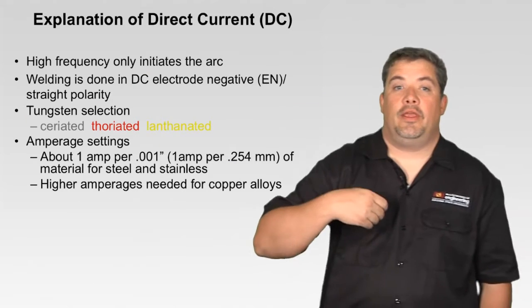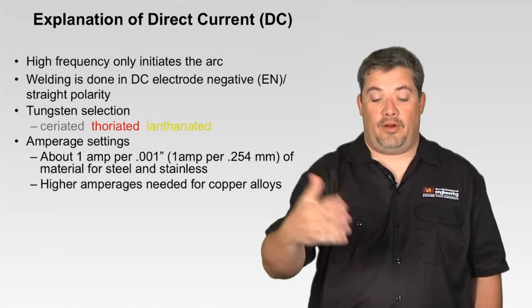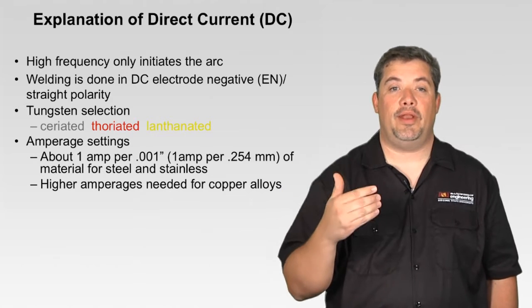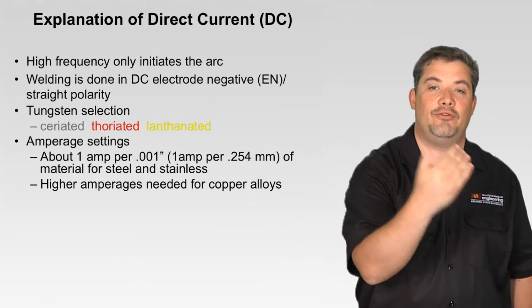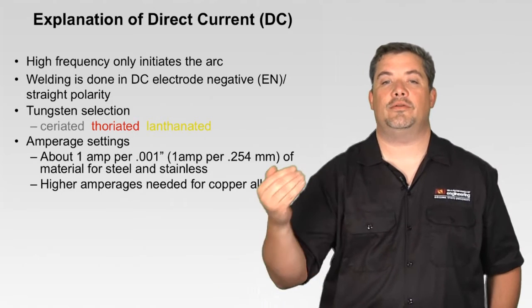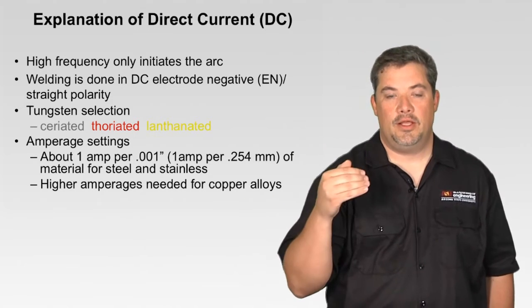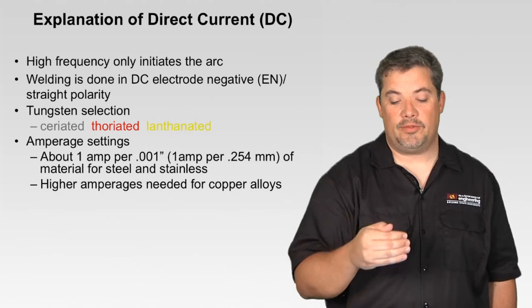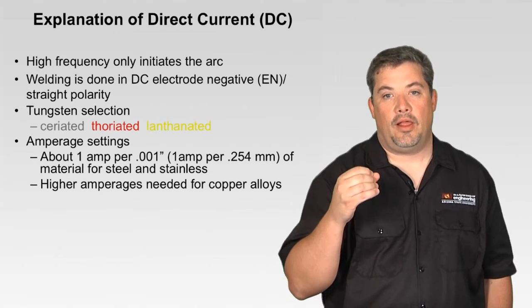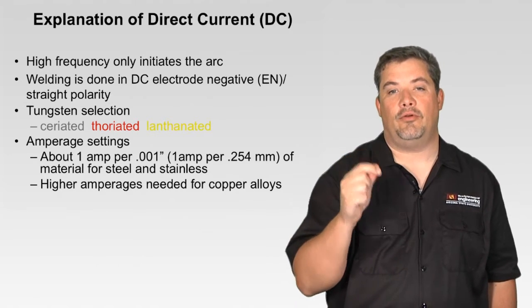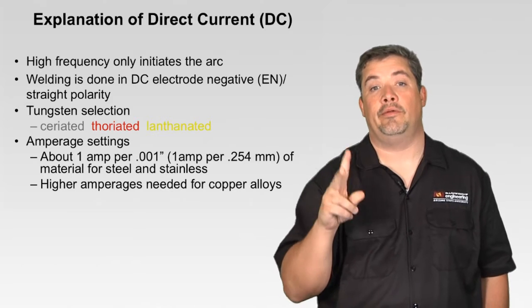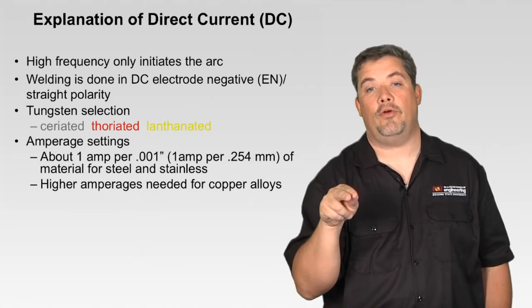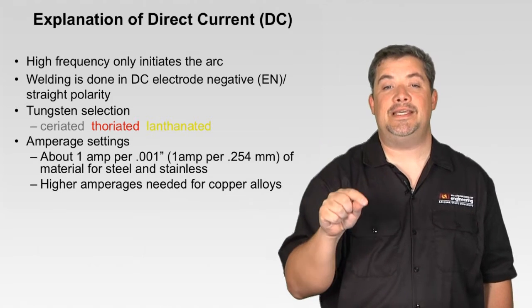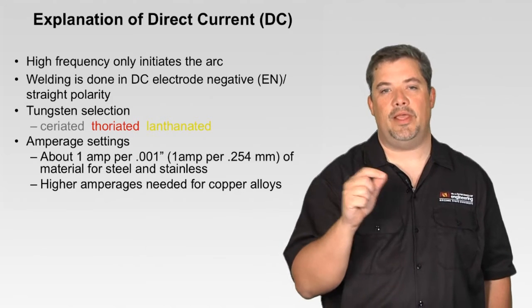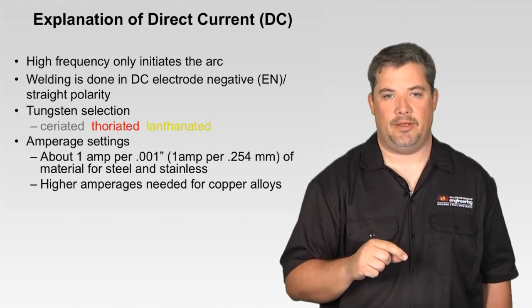So in gas tungsten arc welding, we talked about a lot of the stuff to get up to this point, but now the difference is using direct current and alternating current. So let's talk about direct current quick. In direct current, high frequency initiates the arc. Basically, it's done with direct current electrode negative, also known as straight polarity, which we want to get out of our vocabulary. So DCEN is what we use to weld everything but aluminum and magnesium.